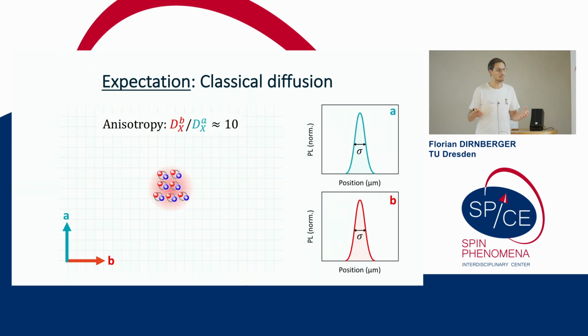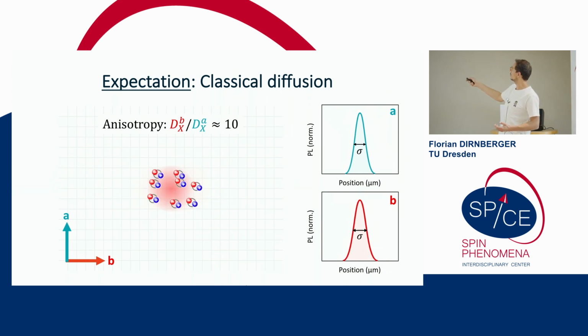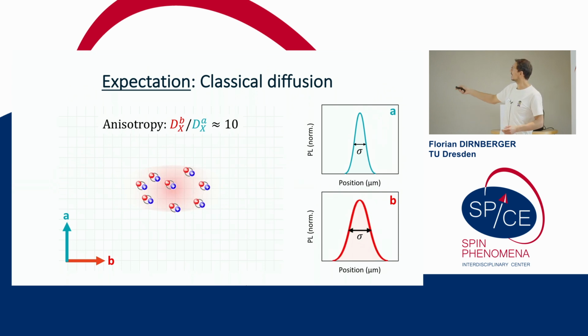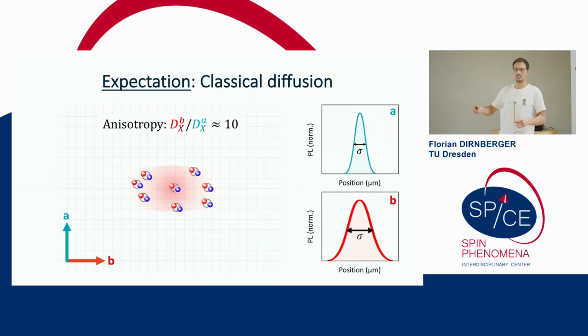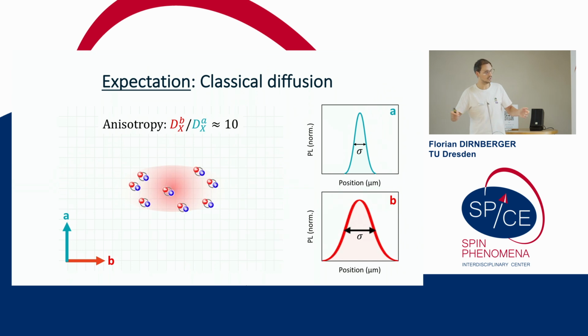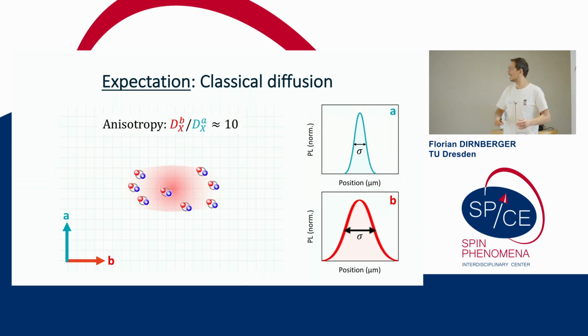This is really what we had in mind when we started these experiments. We shoot laser pulses to create a symmetric distribution of excitons, and then as a function of time and space in this experiment, we can track how the width of that distribution changes along the A and along the B direction. Because of that anisotropy, we would expect that this distribution grows faster along the B direction with the light mass that characterizes the excitons, and then we don't expect to see much along the A direction because they're really heavy, 10 times the free electron mass.